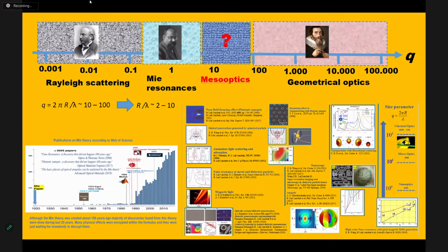Now, if we combine all of these limiting cases, you can see that for small size parameter, that is the case of Rayleigh scattering. For big size parameter, that is the approximation of geometrical optics. And with size parameter of the order of unity, we have the region of so-called Mie resonances, which is quite important for modern nanophotonics, where people basically are interested in first resonances like dipole, quadrupole, octupole, and so on.